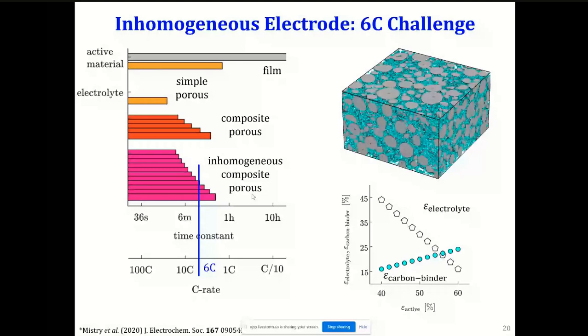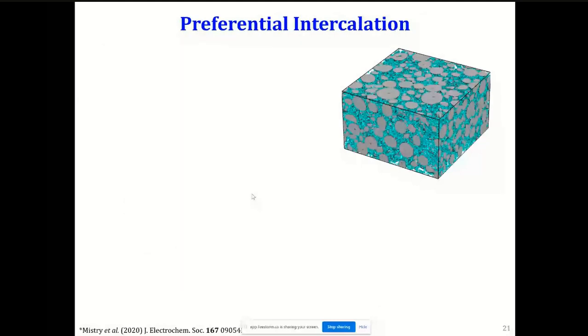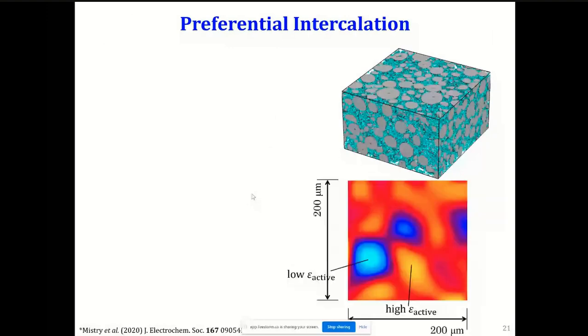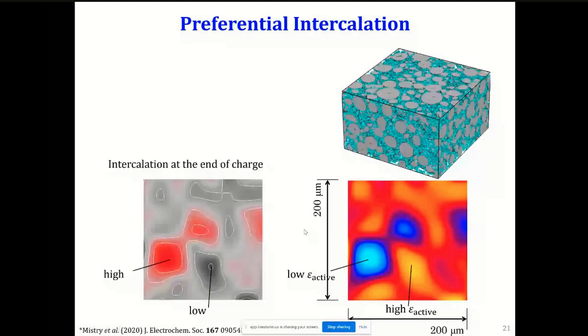So first thing, let us look at the intercalation signature of this when you have an inhomogeneous electrode. I'm showing you the same distribution now as a map, and this is the in-plane view of things. So electrode thickness is across the through-plane, and you have spots which have low active material, spots which have high active material, and if you average over all the spots, you get to your macroscopic value of active material volume. Now, this leads to preferential intercalation. So some spots will get filled in first and would consistently keep getting filled in just because they have lower resistance. And it's intuitive to see why.